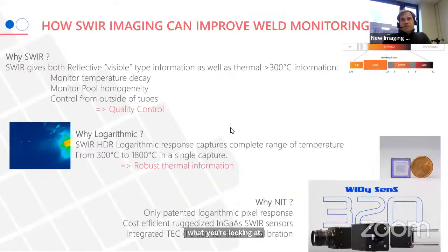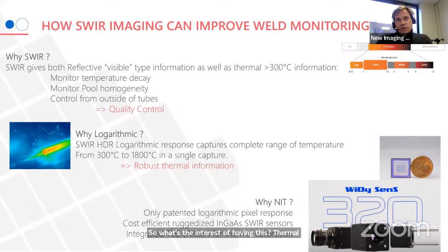The focus today is to discuss how shortwave infrared can also be beneficial for the application. The benefit of shortwave infrared is that it's a wavelength between the near infrared and the thermal 3 to 5 or 8 to 12 micron wavelengths. And so the interest of having this waveband is that it gives both visible, reflective information, but also thermal information for any temperature that is above 300 degrees. So the interest of having this thermal information is that during the process, you can control the temperature or the homogeneity of your pool. You can also control the temperature decay, which is also a good sign of the quality of the welding.